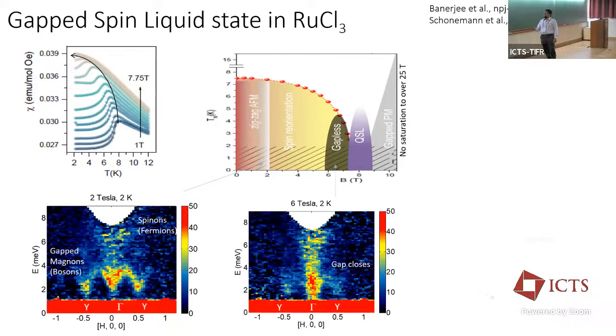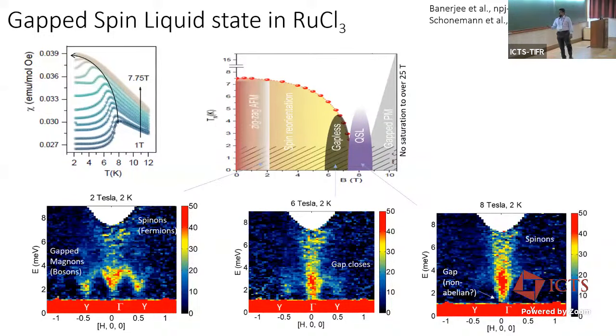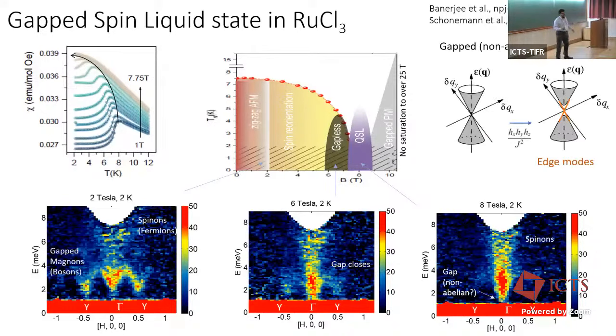And what we find at 6 Tesla is that the gap completely closes and the magnons basically start to vanish, while at 8 Tesla, the magnons have completely vanished, leaving behind what looks like a gapped spin liquid phase with a continuum of scattering right here. And that really made us wonder: is that the gap which was proposed by Alexei Kitaev? Is that the gap that we are seeing here? So that was really what we thought was the interesting question.